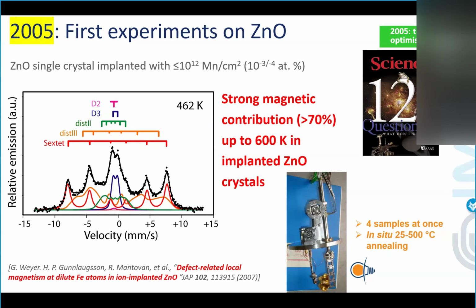And this is a typical lead that we use at ISOLDE. You can see 4 holes. You can place 4 samples at once, and then by moving these halogen lamps up and down, you can anneal them locally from room temperature up to 500. So you can make a lot of measurements by changing the sample and then implanting again. Due to the tiny fraction that you introduce every time, you don't risk having precipitates because you are in a real extremely dilute configuration.